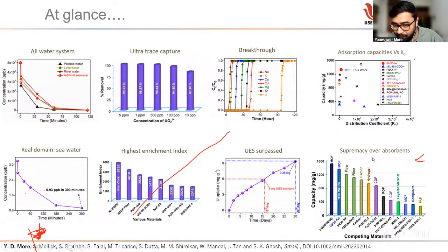So what is the supremacy of the given MOF system over all other adsorbents? Now I will give you the competing materials existing in the market. You can see PAF, the most known material, is the fibers. Why fibers? Because fibers are very stable in the seawater. Seawater is a leaching medium. It has a high amount of salinity and it leaches metals and many ionic compounds, but does not affect polymers like organic polymers. So fibers and carbons are the true competition in that domain. And our MOF is ranked second in the global competition. We have published one more MOF by one of my colleagues which ranks first in this case. So this MOF now has commercial potential, but there are certain problems in commercializing crystalline materials that we will discuss in the Q&A session.